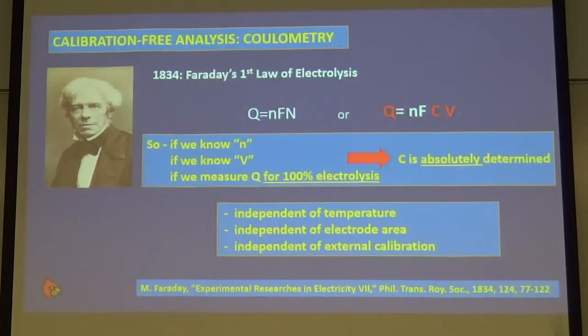So our concept is that if you create a cell of fixed volume, so you know the volume, then you electrolyze it completely. So you oxidize or reduce everything in that sample, and you measure the resulting charge. Then you can calculate C. It's the only thing left. This is a technique, coulometry, but in particular exhaustive coulometry, where you oxidize or reduce 100% of your sample, is calibration free. It's independent of temperature and independent of electrode area. There's no calibration standards that you need. So this is the general approach that we're going to be exploring.